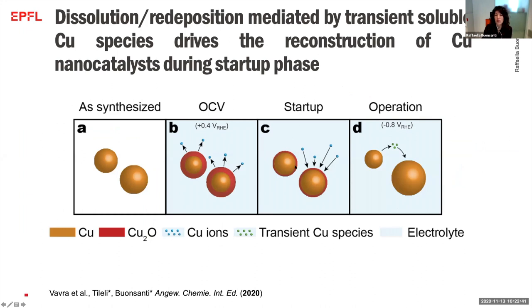Then as soon as we apply the potential, these copper ions initially released in solution start to redeposit on the substrate, but then eventually the process continues through intermediate transient species. And now we really would like to identify what these copper transient species are in order to understand the process better and eventually engineer the process that is occurring.